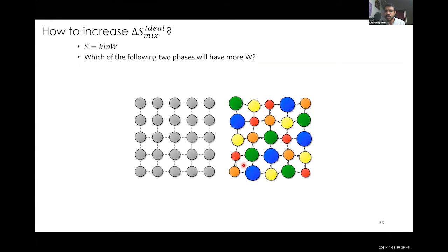Here you have more entities, so the number of ways of arranging them is extremely high. Here it is only one, so there is no W coming from this. Here you will have a very high W value. So having multiple elements in one single lattice increases the W, therefore it increases the S value. If entropy increases, Gibbs energy is going to go down because Gibbs energy is H minus TS. That minus TS term will be very highly negative, therefore the G will go down. If G goes down, the solid solution will be more stable. Whichever has the lowest Gibbs energy is the most stable.